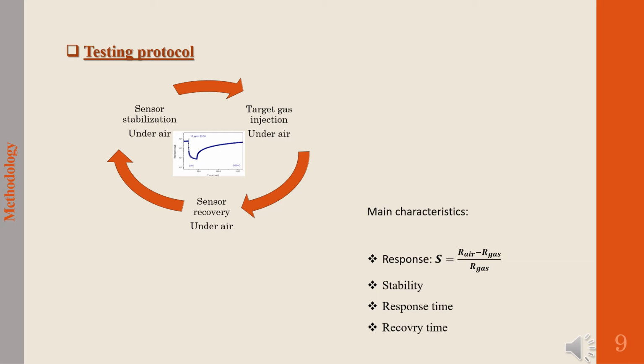The test protocol passes through three steps: sensor stabilization under air, target injection under air, and sensor recovery under air. The performances of the sensors are characterized by different parameters, namely response, stability, response time, which corresponds to the time necessary to have 90% stabilization, and recovery time, which corresponds to the reaction time following the removal of the gas.